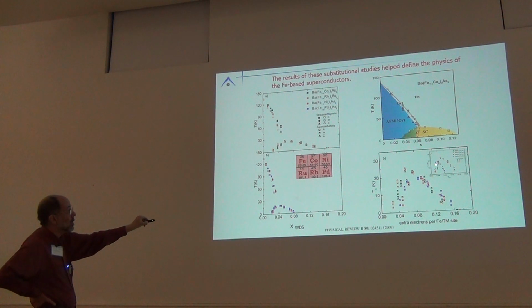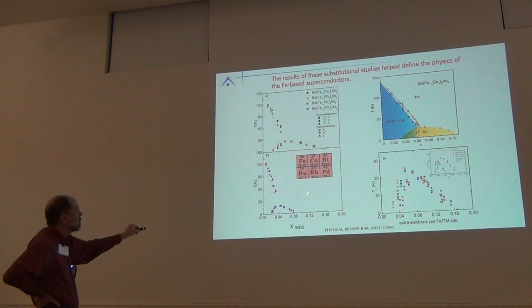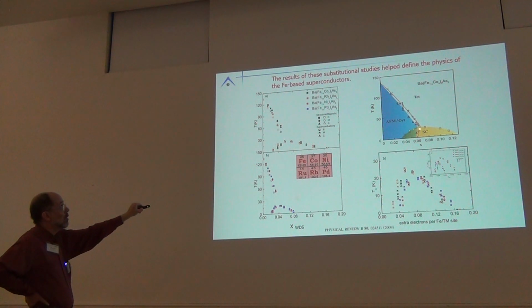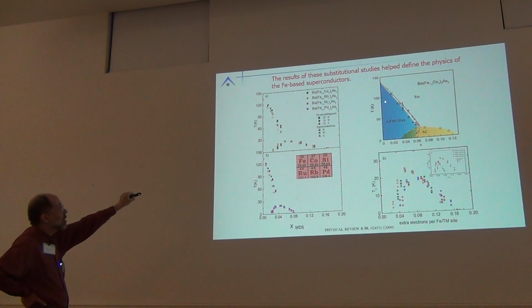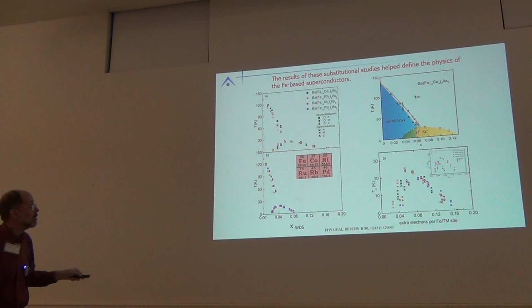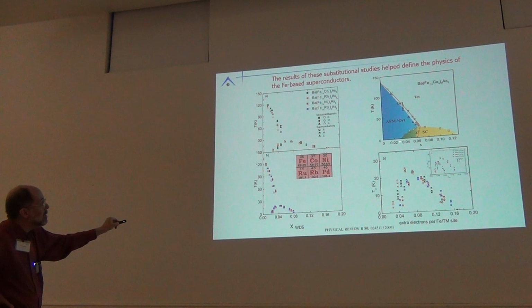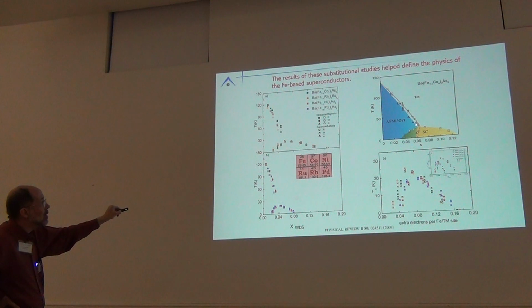Here are the two domes for number of impurity atoms. They're quite separate, but when you just multiply this by a factor of 2, because these add 2 extra electrons as opposed to 1 extra electron, you see the same superconducting behavior. So the archetypical image of the rules of superconductivity in these materials is you suppress the orthorhombic antiferromagnetic transition. In many of these you actually split it, and this gives rise to this whole issue of nematicity. You can see superconductivity turning on as you suppress this transition and encourage fluctuations. You have a maximum TC near a putative quantum critical point, and then TC goes down on the overdoped side.